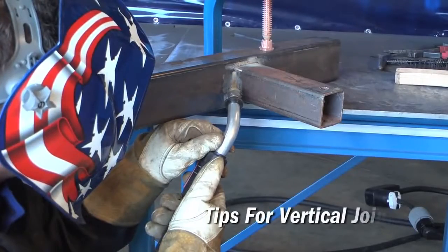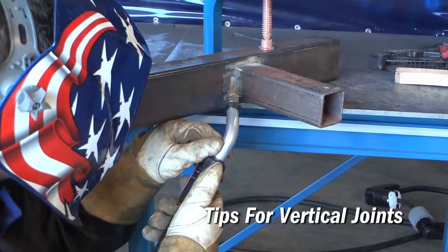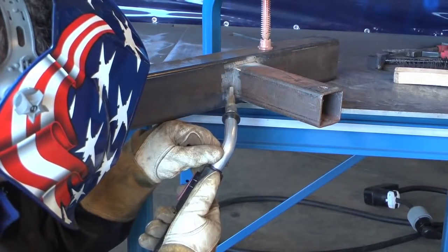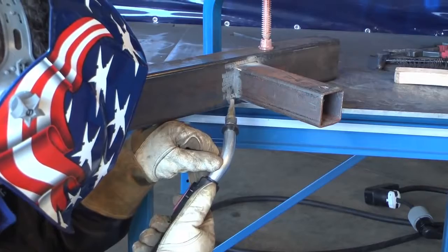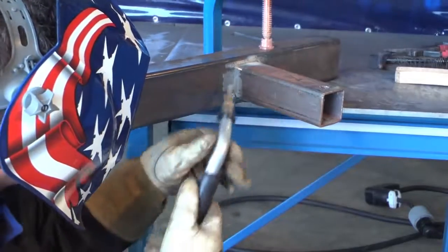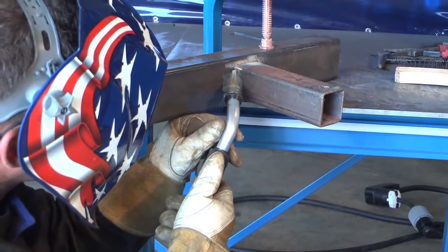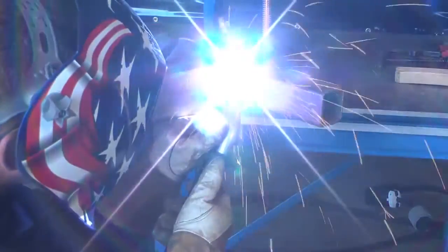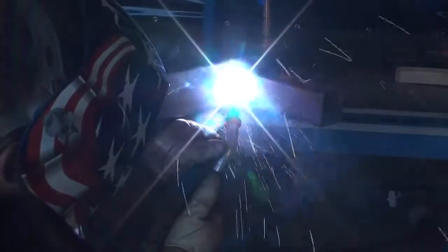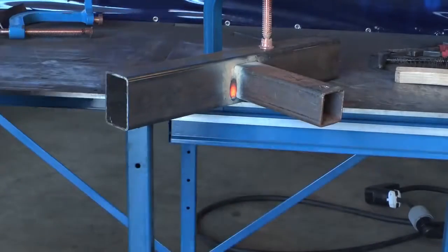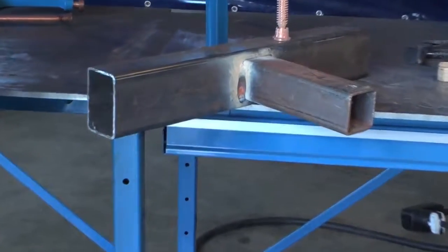For the vertical welding position, again you'll want to turn your machine parameters down by 10 to 15%, and you'll want to angle your gun at 5 to 15 degrees up at the weld puddle. You're going to want to weave from side to side, pausing on the edges to avoid undercut. And also with vertical welding, you can weld vertical up or vertical down. Vertical down will give you less penetration and is much better for thinner metals. Vertical up will give you more penetration for anything 1/4 inch or above in thickness.